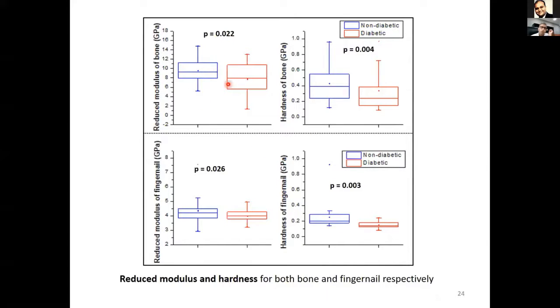We find a clear correlation between the bone and nail deterioration. It means the nail also deteriorates in case of type 2 diabetes, and that is also related with the bone regulation. Maybe we may not need the biopsy. Even by collecting the nails, you can have some estimation of how much bone loss is happening in case of diabetes. As well as, in another paper we have shown that the nail can be a screening tool for type 2 diabetes, but you have to investigate a lot of parameters, not only this nanoindentation parameter. Other parameters we have also investigated, which are in our paper. But here I'm talking only about the nanoindentation, right?